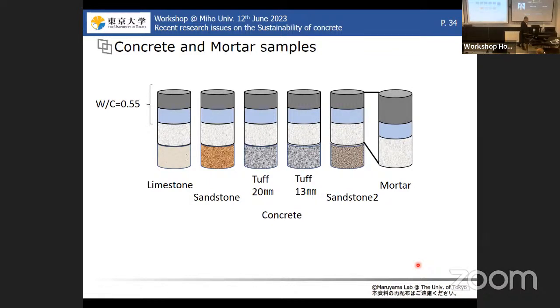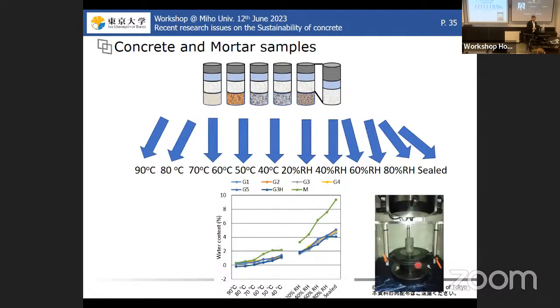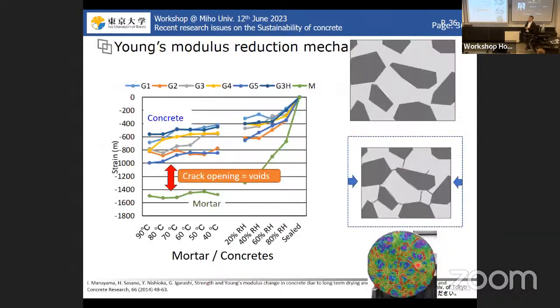And then after the long-term curing period, we put the specimen in different drying conditions for a long term. And these are the desorption isotherms, the water content of the concrete or mortar. And then we measured the Young modulus. I also measured the shrinkage of concrete and mortar.